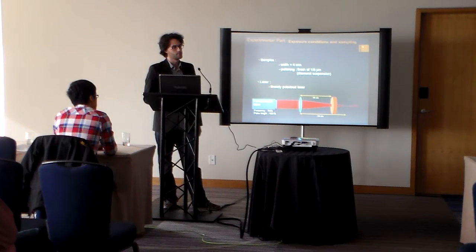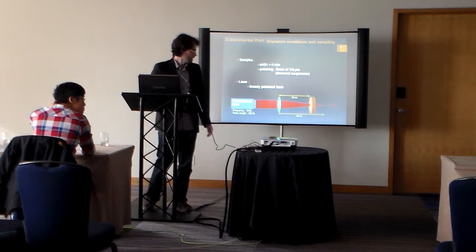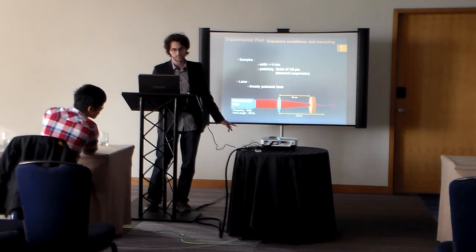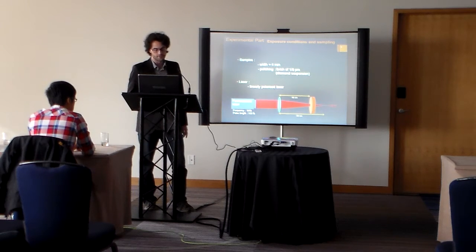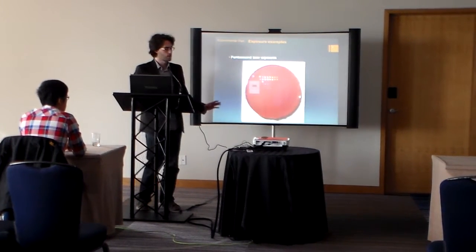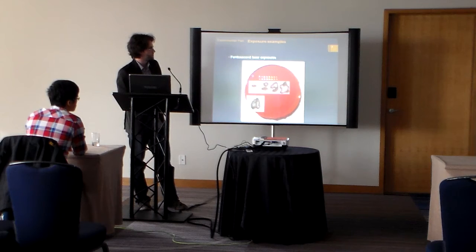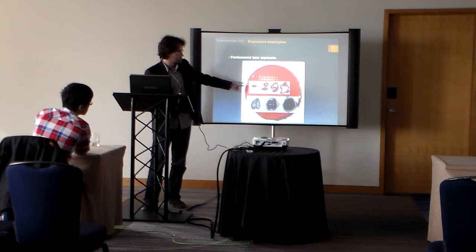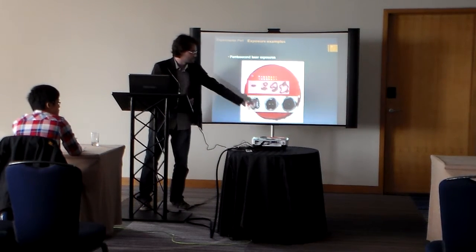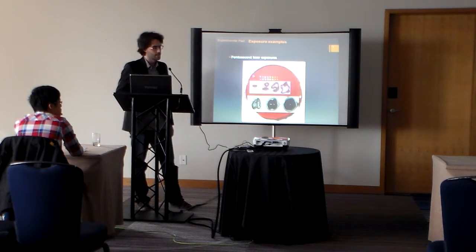The laser used is a femtosecond pulsed laser with pulses of 100 femtoseconds with a frequency of kilohertz. Samples were put at a distance of 46 centimeters, so the beam radius was 0.5 millimeters. So here are a few examples of exposures. We start with short time and low power levels, and go all the way to high power levels with a long time exposure.